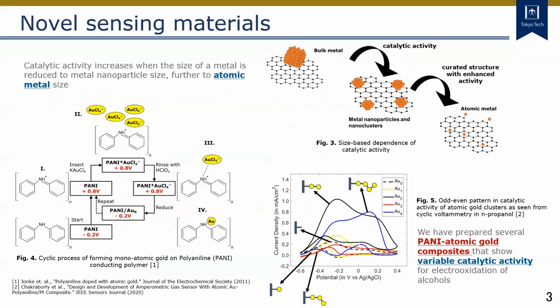From other works of heterogeneous catalysis, it has been shown that when the size of a metal is reduced to nanoparticle size, its catalytic activity is improved. This activity is further enhanced when the size is reduced to monoatomic metal size. Curated structures of atomic gold can be and have been formed on conducting polymers such as polyaniline. Figure 4 shows the fabrication process of a single atom of gold on polyaniline, or PANI, conducting polymer through a bottom-up electrochemical process. Polyaniline can be oxidized to create a metal binding site, and a metal-ligand bond can be formed by a suitable metal precursor.